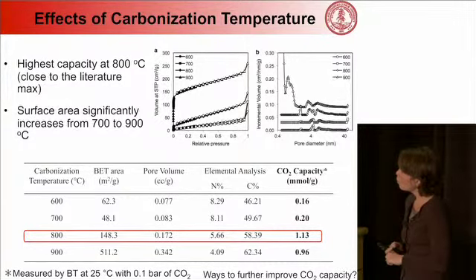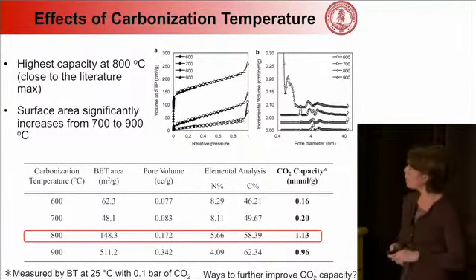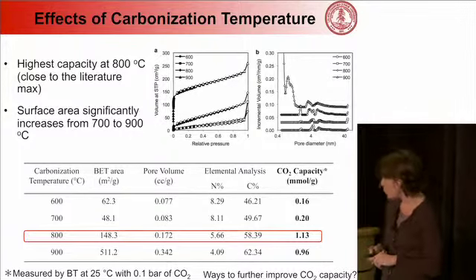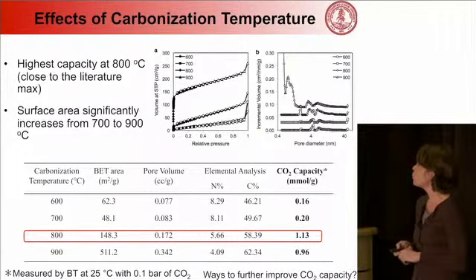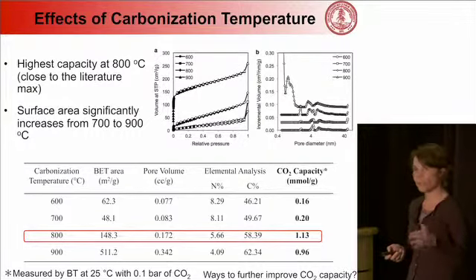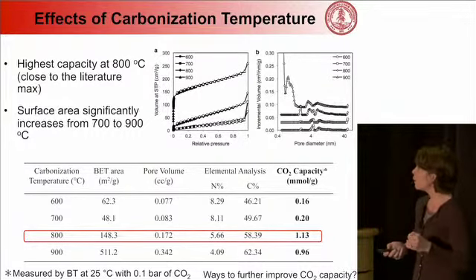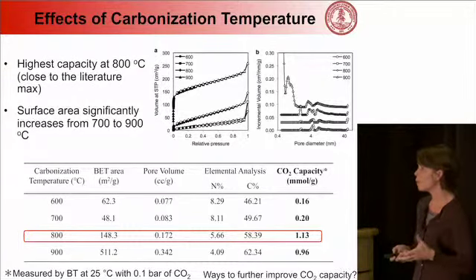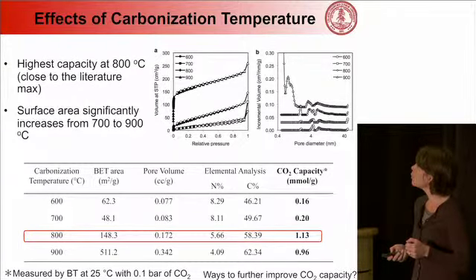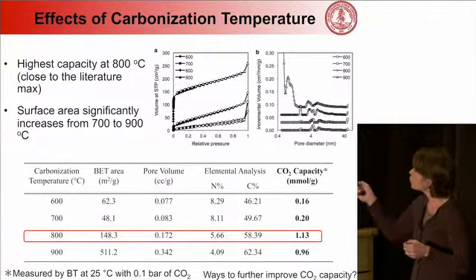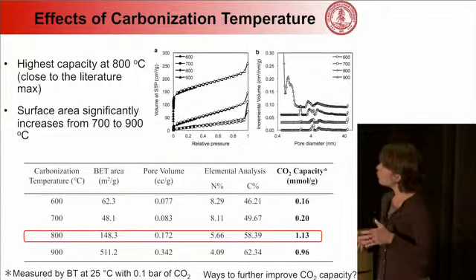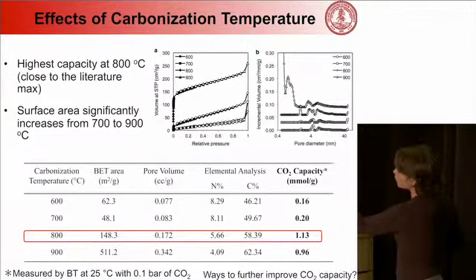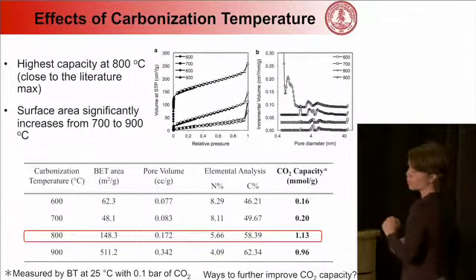surface. And so what we're showing here is that the enhanced capacity, which we find to be about 1.1 in terms of millimoles per gram, which is pretty consistent with what I showed in the previous slide of the previous results, and again at 25 degrees C and 0.1 bar, the same conditions. But what we find is it's this 800 degrees C carbonization temperature, which leads, if you look in the upper right, and it's the open circles, which is the second plot down. And so it's difficult to tell, but there's a pretty non-uniform pore size distribution in that second plot.